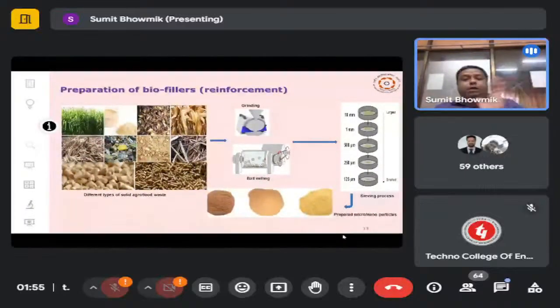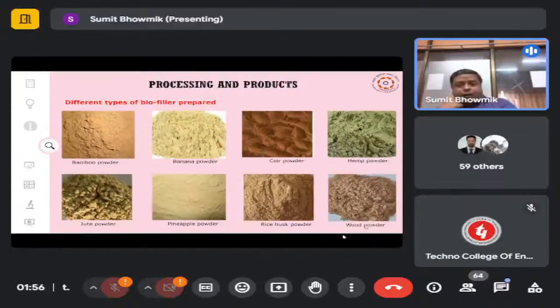In that case, whatever fiber or filler shape we collected, first of all, that has to be ground, and then it has to be placed in the ball mill so that fine micron level filler can be developed, and that has to be categorically classified into different groups. For example, the smallest filler we have considered is 125 micron, then 250 micron, then 500, then 1 millimeter, then 10 millimeter. But when it exceeds the micron level, this can be considered as a short fiber. These are schematic representations of different fillers prepared from different resources like bamboo, banana, coir, hemp, jute, pineapple, rice, and wood powder.